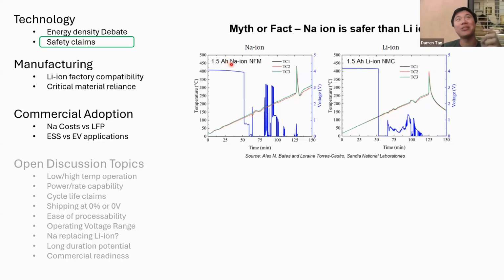So they have a 1.5 Ah sodium-ion cell and a 1.5 Ah lithium NMC cell. And they basically did a barbecue test. They put the battery in a heated chamber and gradually heat it up at a steady rate. And almost at the same point, at about 250 Celsius or so, thermal runaway occurred, and we saw a temperature spike. The amount of heat release was nearly the same. The rate at which temperature rose was also nearly the same. And the conclusion from that study was that for this specific chemistry, nickel-containing sodium ion was as safe or as dangerous as nickel-containing lithium ion.